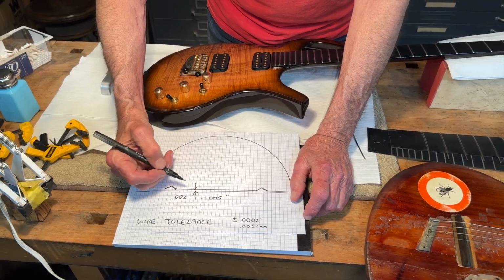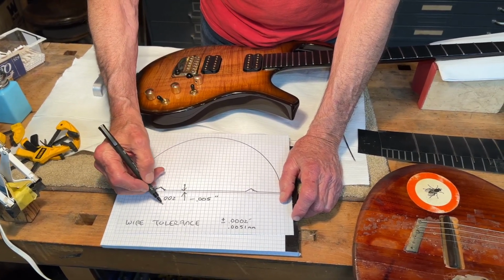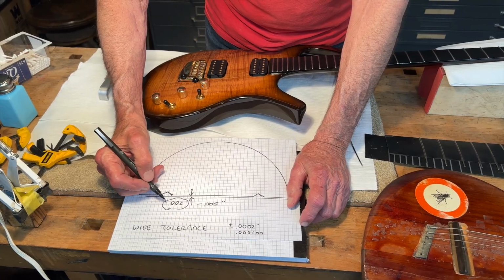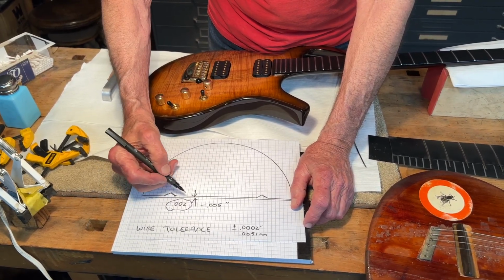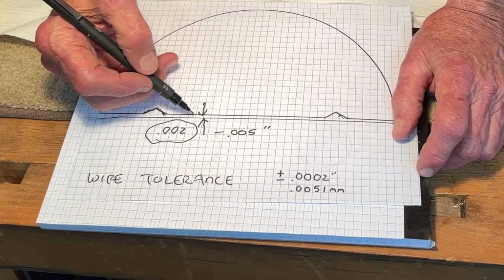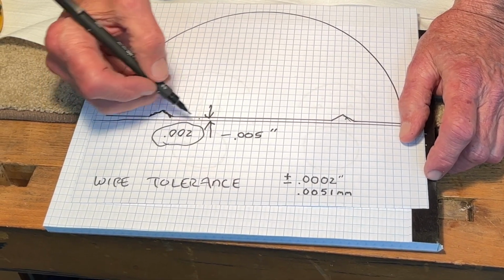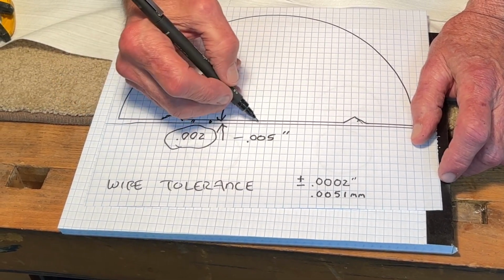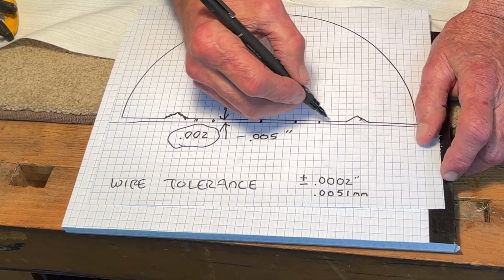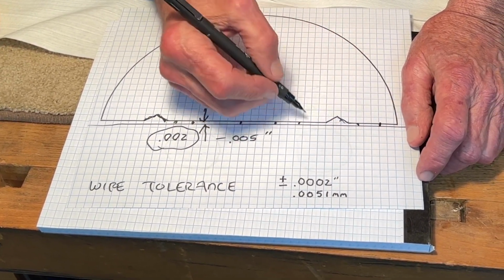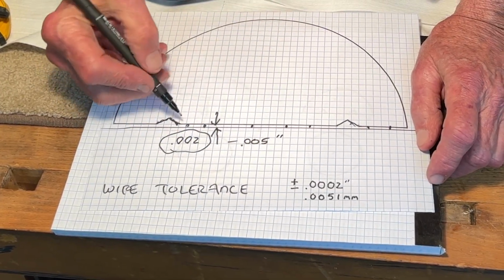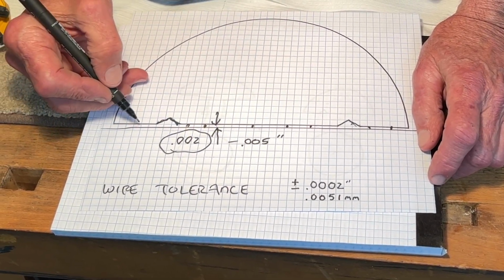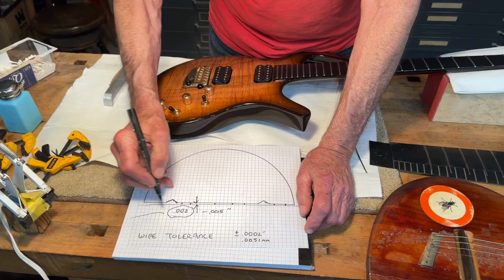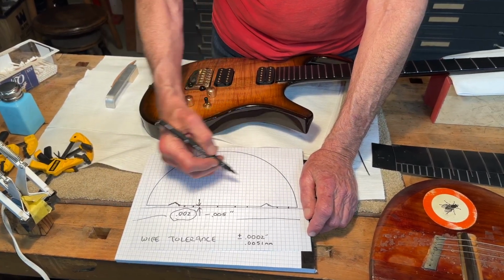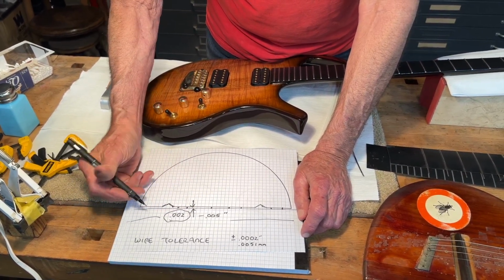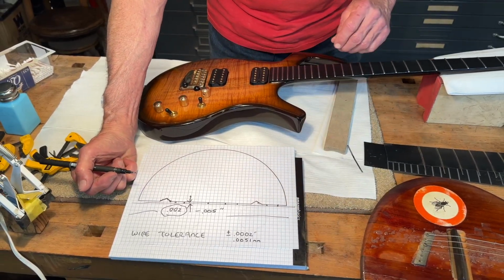That's not much. What we ended up doing was we used some glass beads that were 0.002 in diameter, and we put them on the fretboard. Those 0.002 beads ended up being spacers to ensure that when we clamped things together, we didn't squeeze all the adhesive out, and we had the correct amount of adhesive in between the fretboard and the fret, in order to create the strongest bond line that we could get, which we needed.